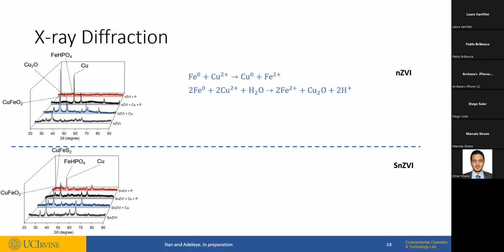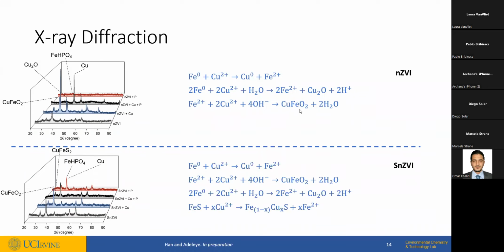And based on this characterization, we can actually come up with equations for the reactions that are occurring. So we do know from the XRD that the iron is able to reduce copper, and that's thermodynamically favorable. But it's not just reduction to copper 0, we also have reduction to copper 1 states. In addition, the dissolved iron formed can actually complex copper as well to form this precipitate here. And on the SnZVI side, the reactions are very similar, but in addition, there is also a precipitation with iron sulfide, in addition to the precipitation with iron 2+.